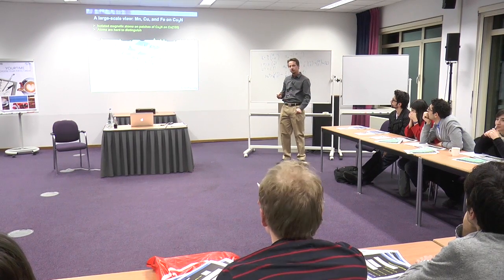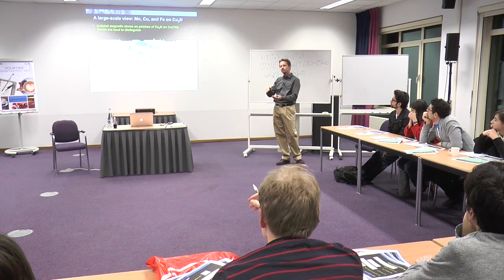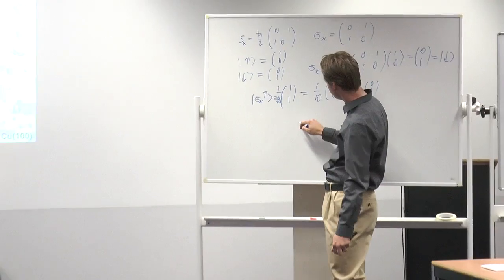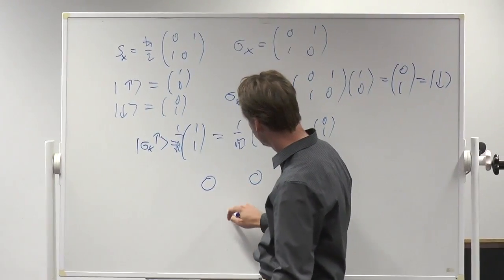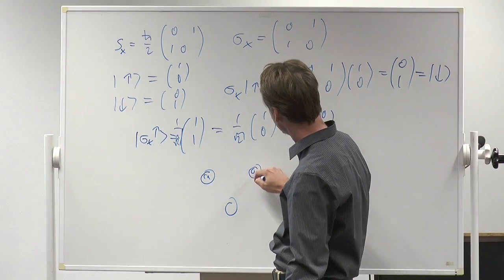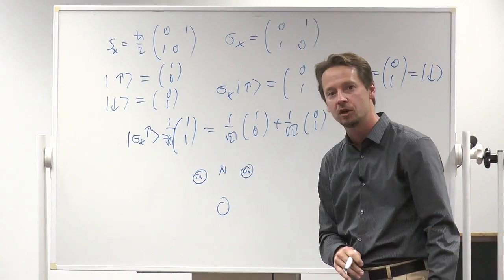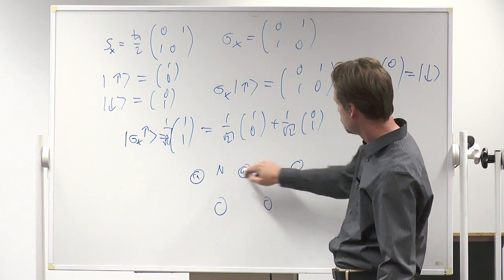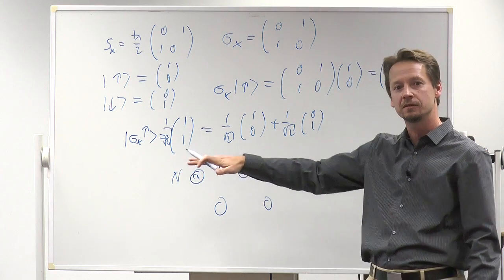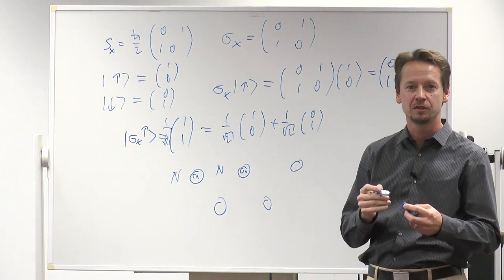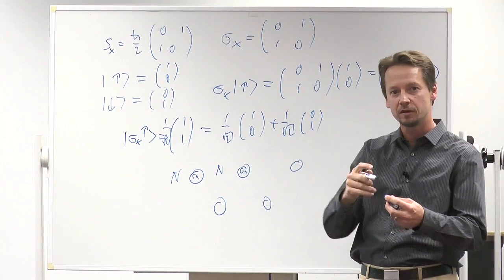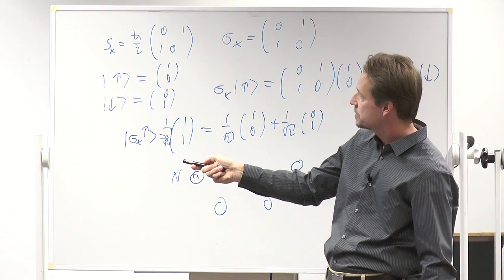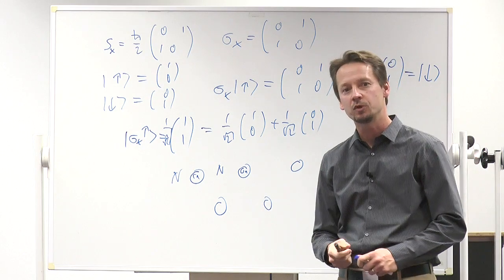Yeah, so the copper nitride is actually laying on the copper. Physically, this is more like this. So you have your copper here, and then the nitrogen is almost sitting inside that copper. So you can think of, if there's an end to the copper nitride, right? So there's no nitrogen, and here's nitrogen here. Then that's basically a planar structure to first approximation. Okay, so it's not sitting on top; it's sitting inside the top layer, and it appears lower here. Right? It appears like it's a step down because of this requirement to keep a constant current.